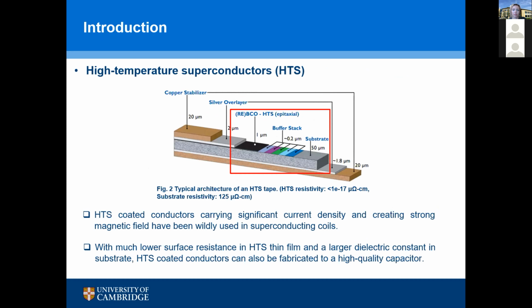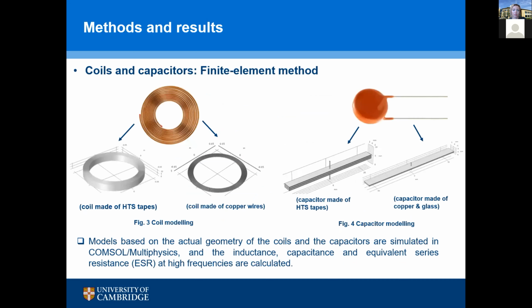Thus, high-temperature superconductors, also known as HTS-coated conductors, are promising candidates for this job due to the almost zero resistance. Most relevant studies aimed at applying an HTS coil in the WPT system because it can carry significant current density and create a strong magnetic field. But few studied the effect of an HTS capacitor. Therefore, we propose that HTS-coated conductors can also be fabricated into a high-quality capacitor with much lower surface resistance in the HTS thin film and a larger dielectric constant in the substrate layer. Let's move on to the methods.